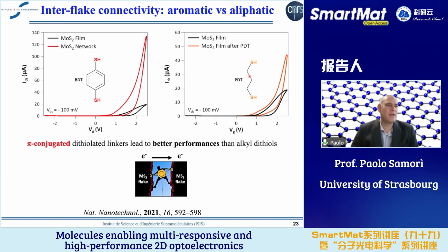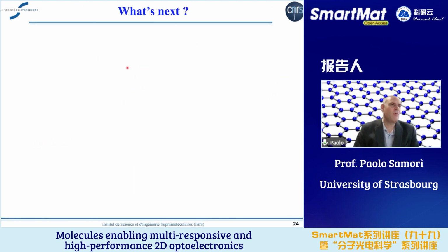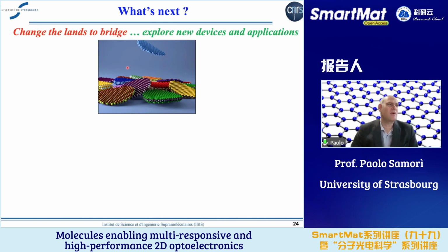So we use a C3 type of alkane, so propane, and we observed that the increased performance is much, much lower when we use an alkane that is not semiconducting compared to the benzene. So what is next? What is next is that you can think of using this kind of networking approach for different types of 2D materials, depending on the type of application you have in mind.